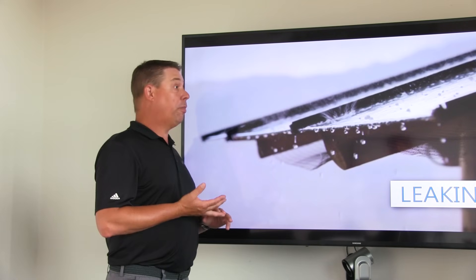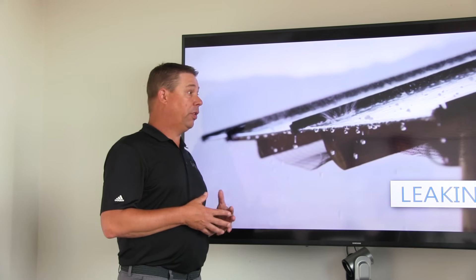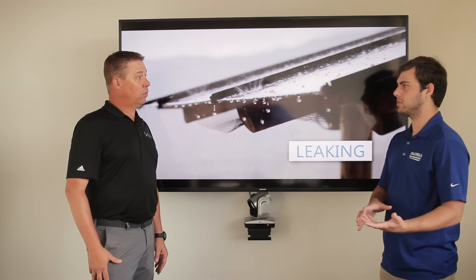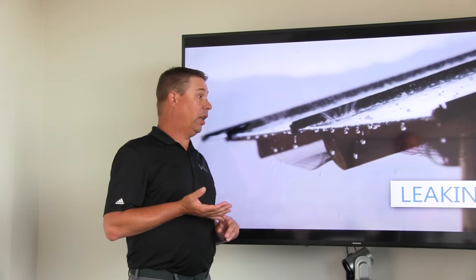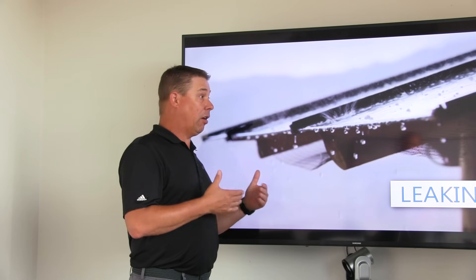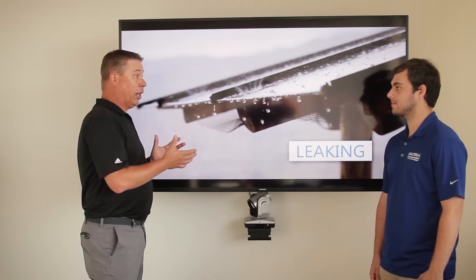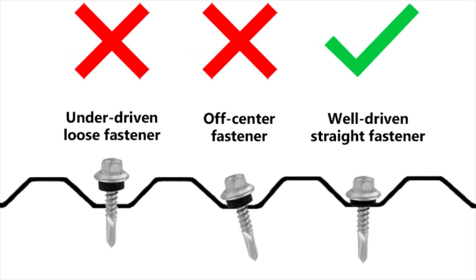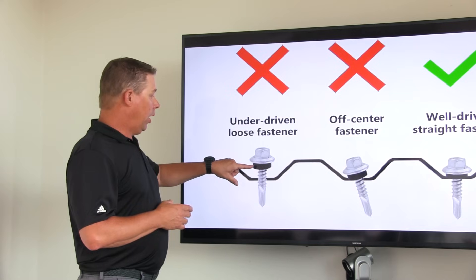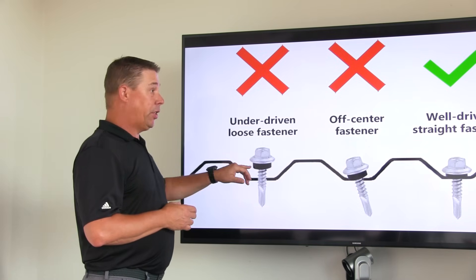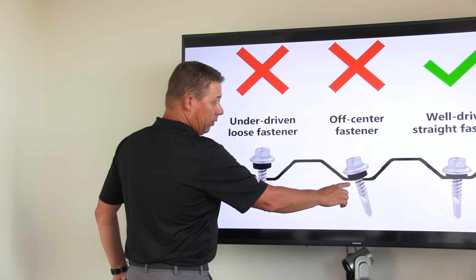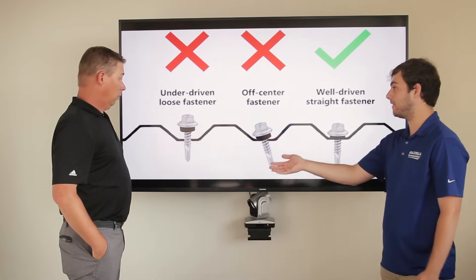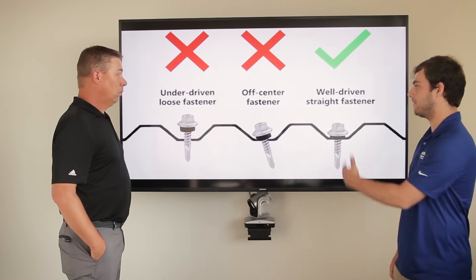It could be a bad installation, it could be a major weather event — sometimes you get rainstorms and your roof condition is just overwhelmed with the amount of water. The most common one I see is unfinished business: whether they just have not finished the counter flashing, one area got forgotten, or the installer didn't quite get there. The other one is on a face-fastened panel — the screws themselves. The biggest problem is the neoprene washer is unprotected from UV, so it will deteriorate very fast. You might have a roof installed and be okay for a while, but eventually you're going to start seeing leaks where fasteners are under-driven or off-center.